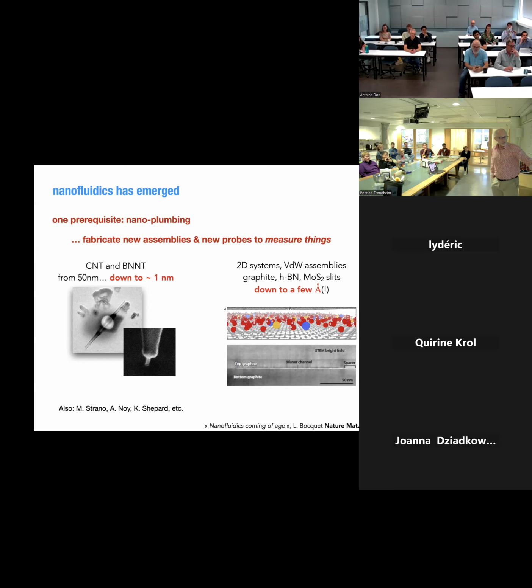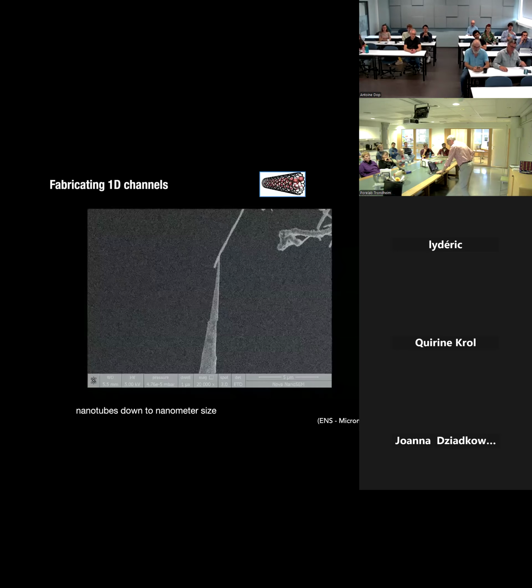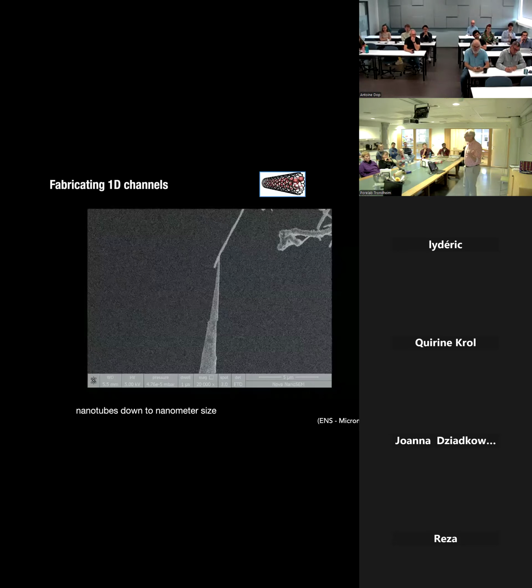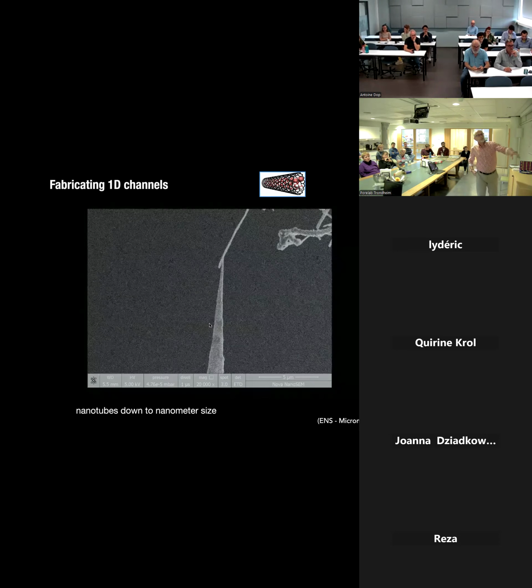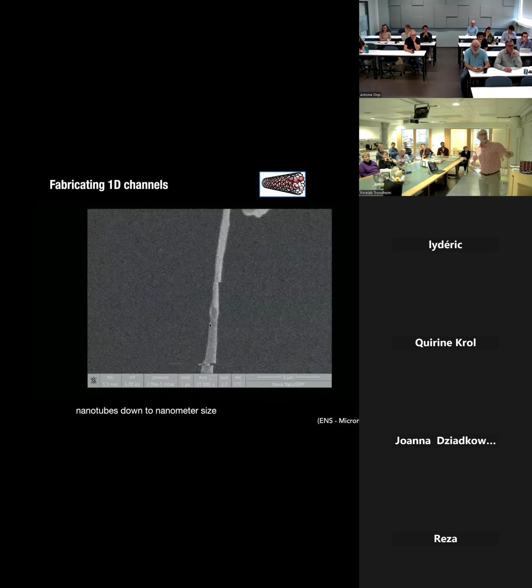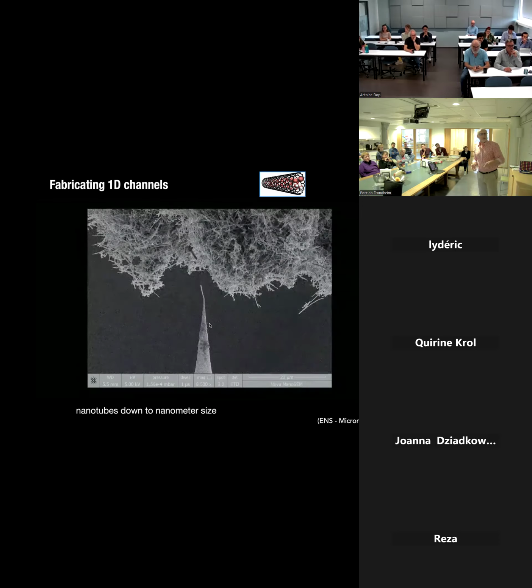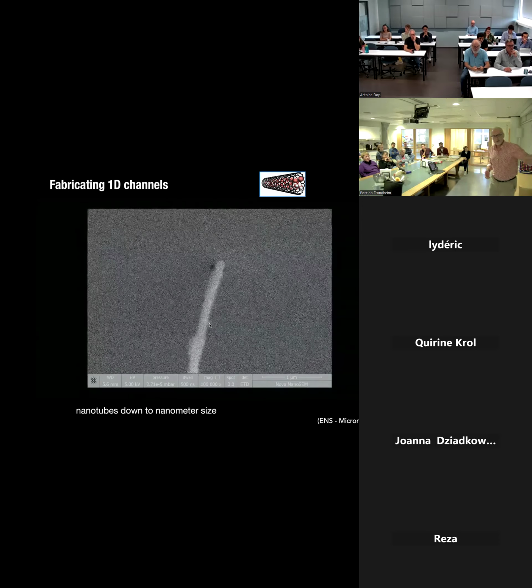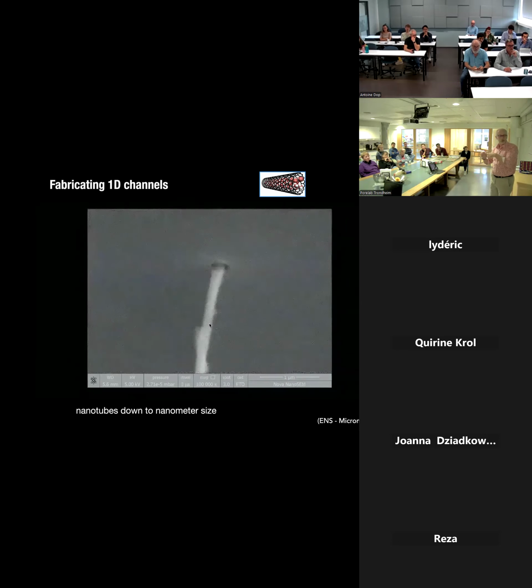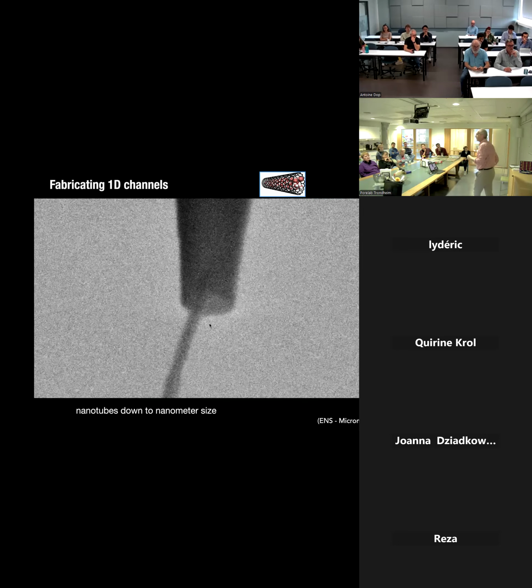And also, I will tell you more about 2D channels, where the thickness goes down to a few angstroms. So just to give you one flavor, that's how we fabricate systems in Paris. So we use nanomanipulation under the SEM of carbon nanotubes or boron nitride nanotubes. This is a real-time movie. So basically, this is an STM tip. You pick up one nanotube in a forest, which you can buy, and you take this and you insert it using a 3D motor inside a hole. And at some point, you see here, you can glue it.